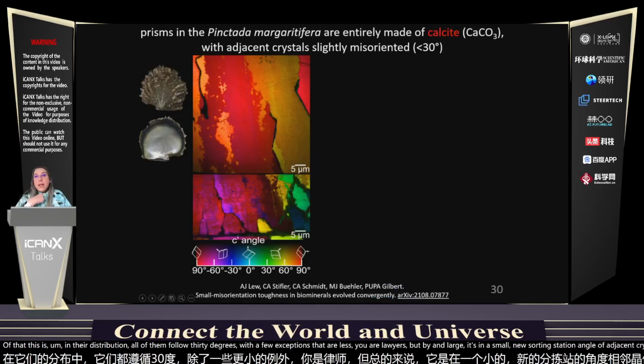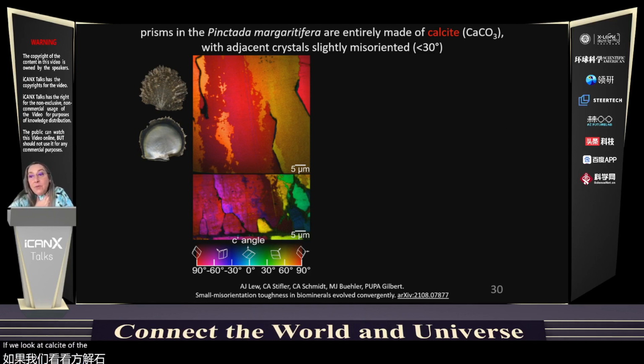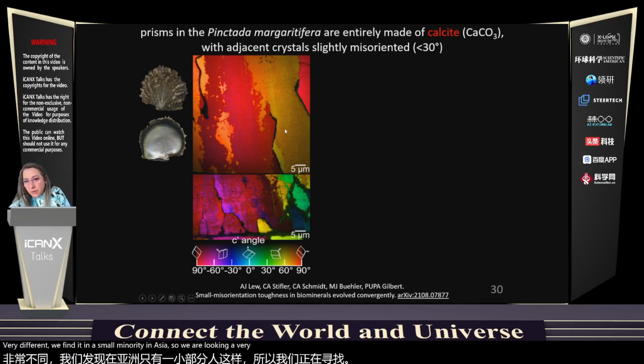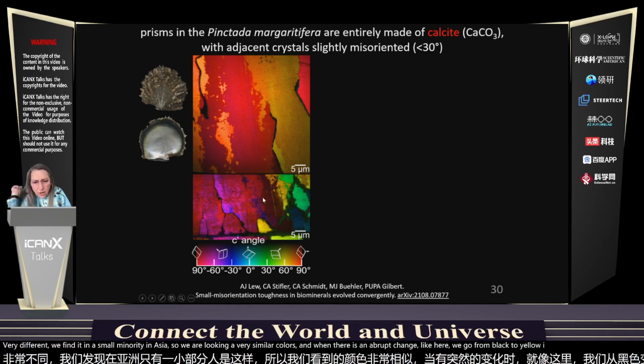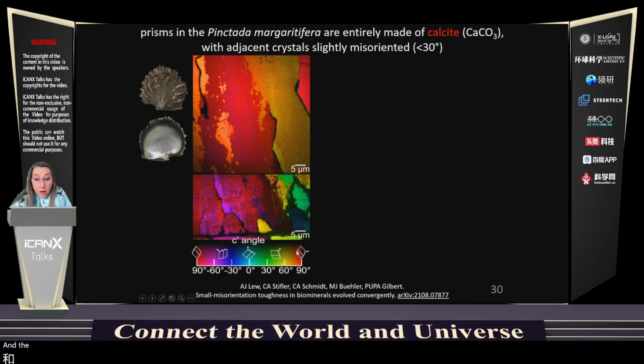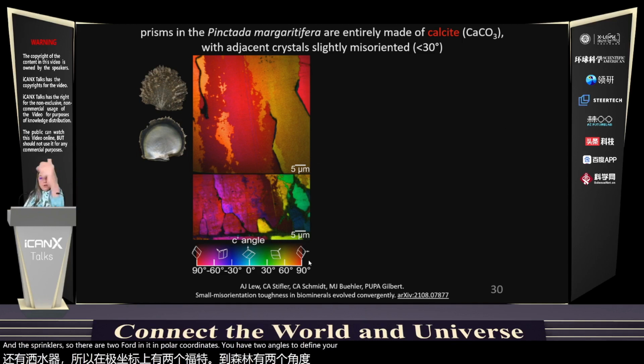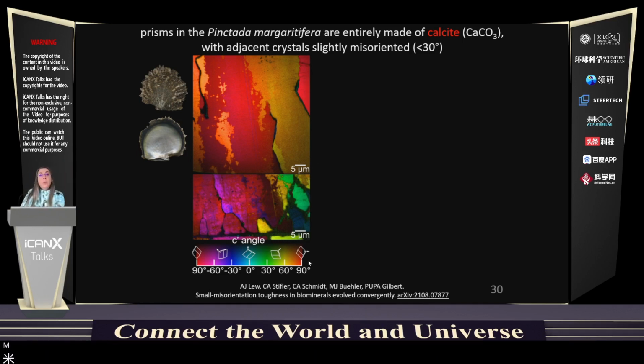crystals. If we look at calcite on the outside of a pearl oyster, Pinctada margaritifera, we find again a small misorientation. So we are looking at very similar colors. And when there's an abrupt change, like here we go from black to yellow, I should have said earlier, actually, these PIC maps are displaying colors. So there are two coordinates. In polar coordinates, you have two angles to define the orientation of the c-axis of any vector. And it is an in-plane angle and an off-plane angle.